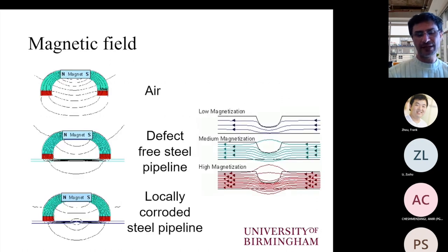So the principle of magnetic flux leakage is based on magnetizing the sample, as I said earlier. And of course, in order to magnetize it, it has to be ferromagnetic. You can see on the left-hand side the series of schematic diagrams. You can see how the flux distributes itself when we have no ferromagnetic component in the vicinity where the flux field is present. And then when we have a pipeline which is defect-free, then the sample will be magnetized, but no flux leakage or no sufficient flux leakage will occur in order to give us a measurable signal.